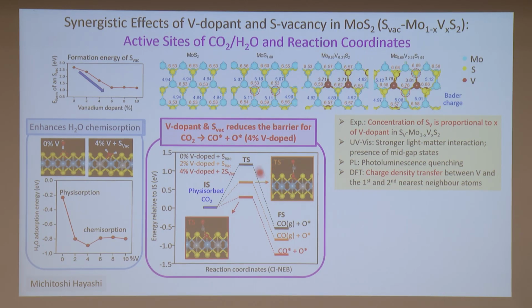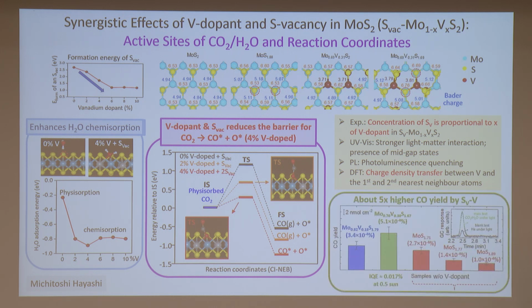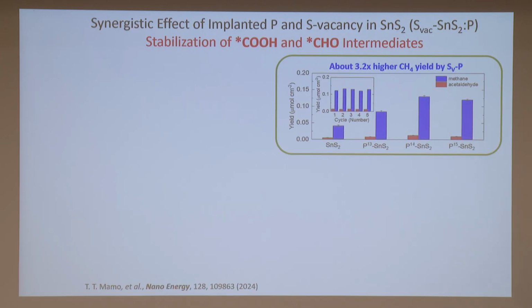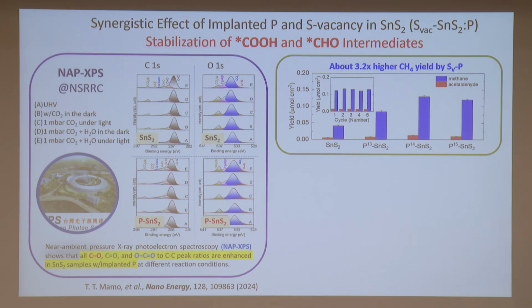So this is a transient state, and the one with the vanadium of 4% actually reduces much so that this can occur, that they transform to CO. And this is the yield by the GC measurement. So indeed, we have about 5 times higher CO yield if you do the doping. Okay. And by implantation, we also see if we have maximized the dopant in such a manner, we can also increase by 3 times, in this case, it's methane. And this is the GC result.